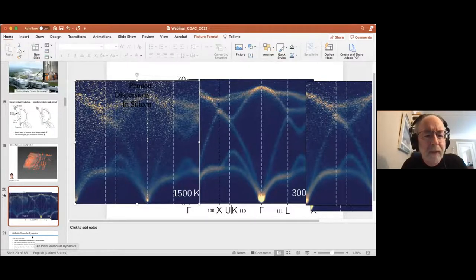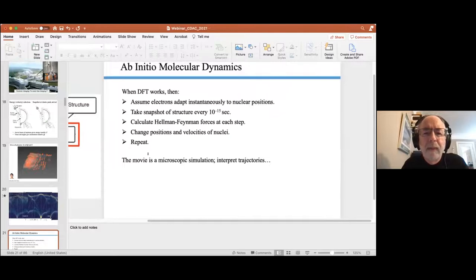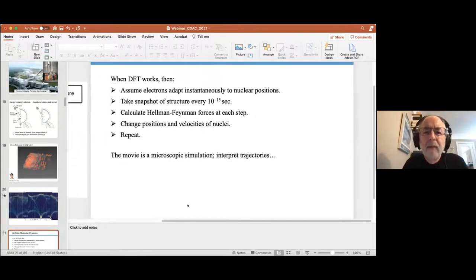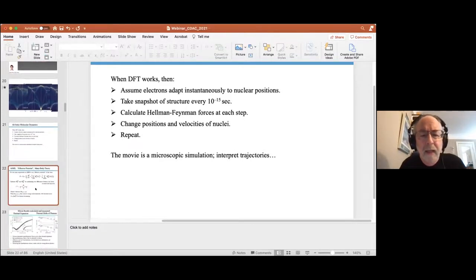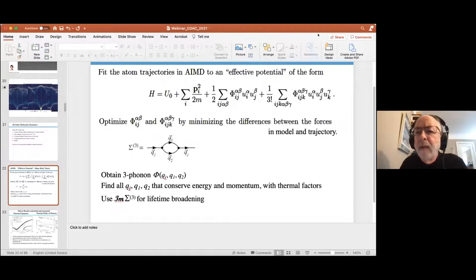They decrease in frequency. And we've done some work to interpret these with ab initio MD. This is basically making a movie of the atom positions and the trajectories of them individually and time steps that are much shorter than the highest frequency phonon. We get the usual iteration where we recalculate the Hellman-Feynman forces at every step. We move the nuclei a little bit, change their positions and their velocities, and repeat. So this is one way of doing a study of the phonon dynamics.